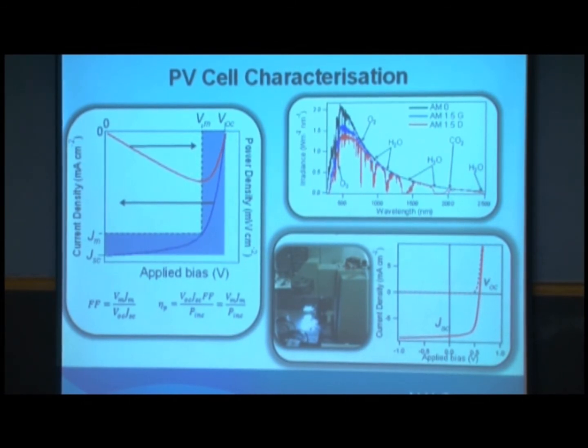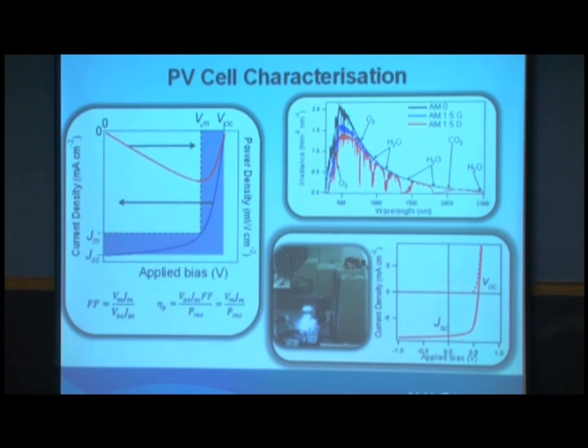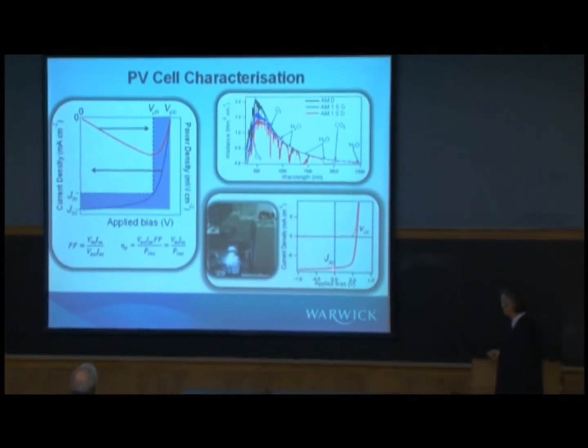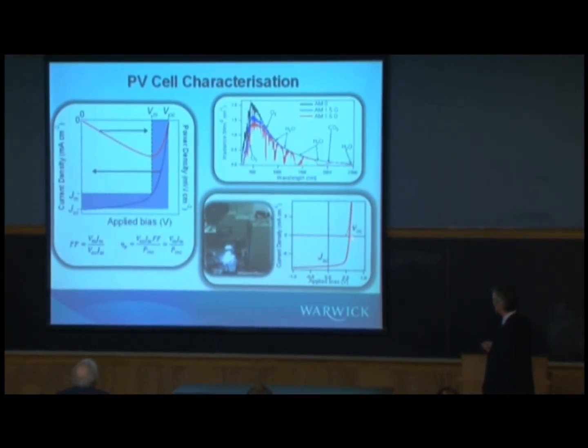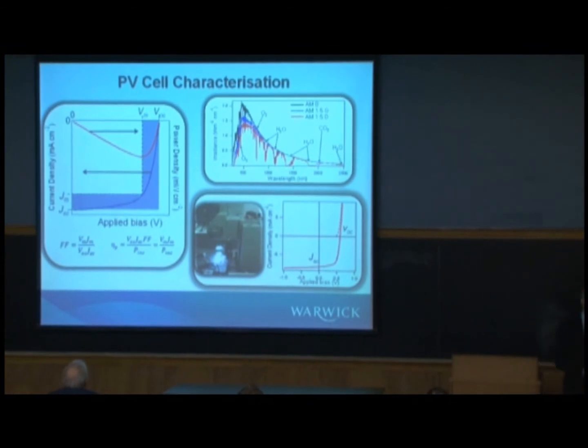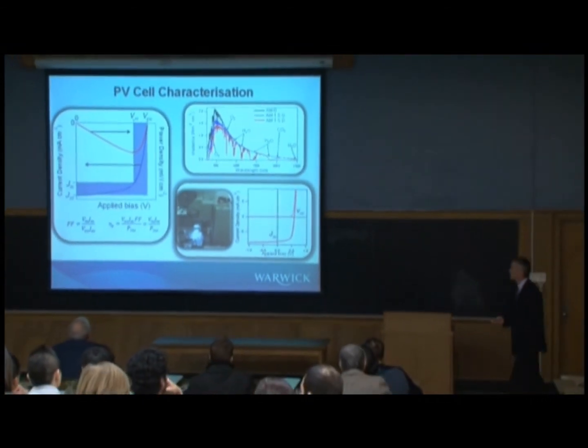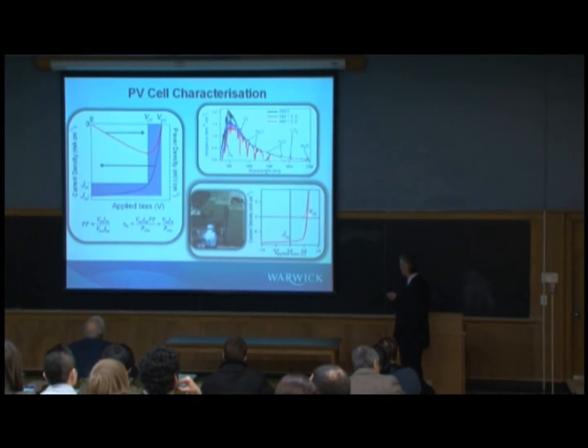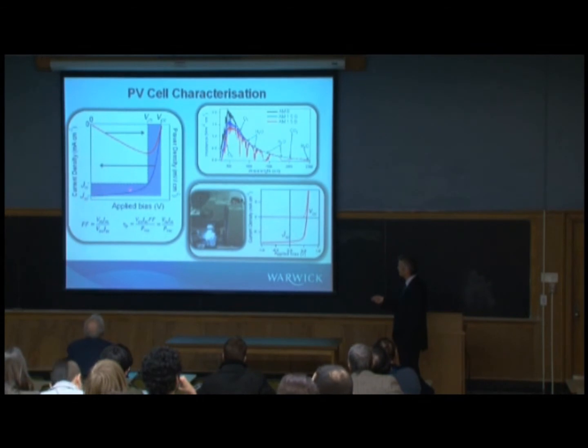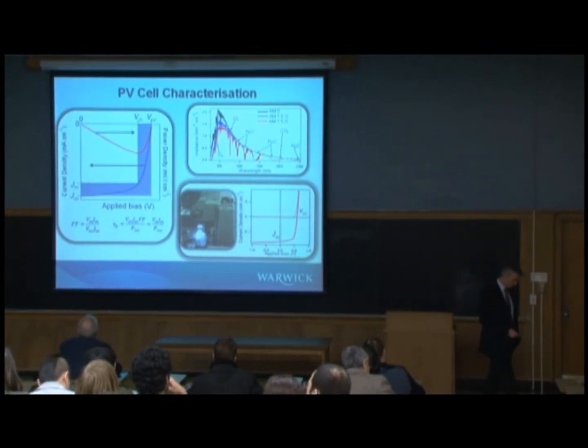And basically, you take the current-voltage characteristics of your cell. In the dark, it would be a diode, like so, the dashed line there. And then under illumination, you'd get the solid red line here. The key characteristics that we're interested in are the short circuit current, the current here at 0 voltage, and the open circuit voltage, the voltage here at 0 current. And the bit of interest for a solar cell is this fourth quadrant here, which is blown up here, in blue now. So again, we have the short circuit current and the open circuit voltage.